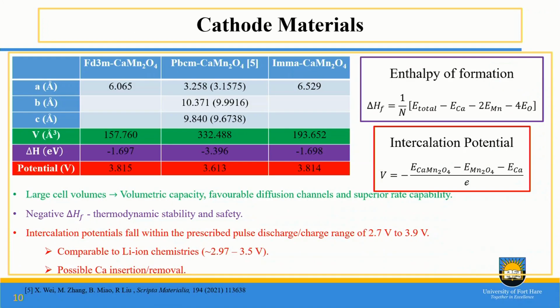So we have done some calculations on these 3 polymorphs. We have calculated their structural properties. We have calculated their enthalpies of formation. We have also calculated their projected operating potentials, or the potentials that can be used when they are in operation. Then we can see that the PBCM structure as well as the IMMA structure have a very large volume, which also offers good volumetric capacity. It can also offer favorable diffusion channels and superior rate capacity as compared to the FD3M, which is a cubic structure. The other 2 are orthorhombic structures.